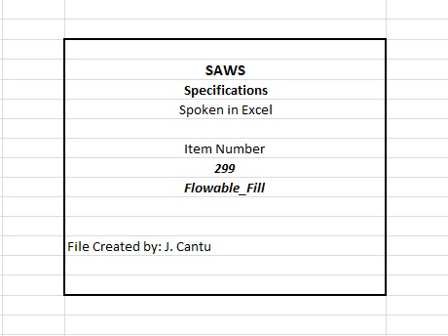3. Shrinkage and bleeding. Limit shrinkage to 0.5% or less based upon the results from a ASTM C827, change in height at early ages of cylindrical specimens from cementitious mixtures. A. Batch, mix, and transport flowable fill in accordance with ASTM C94, except when directed otherwise by the engineer. B. Mix flowable fill in quantities required for immediate use.